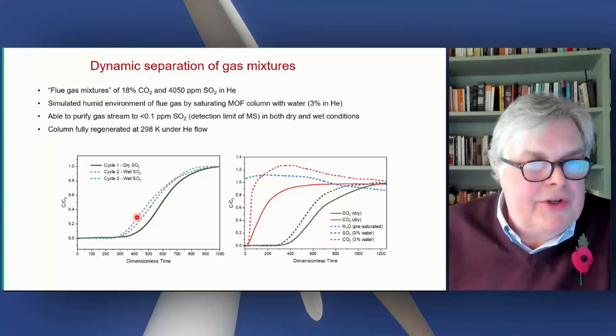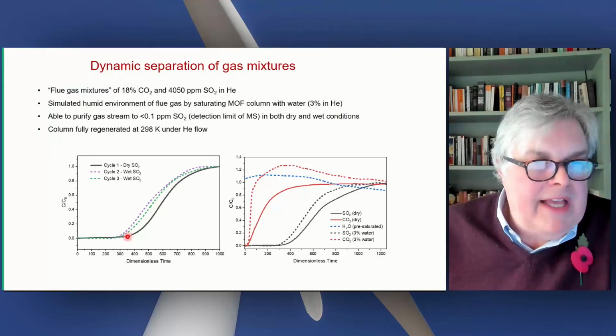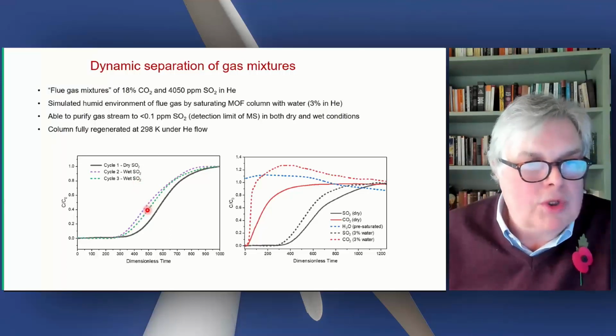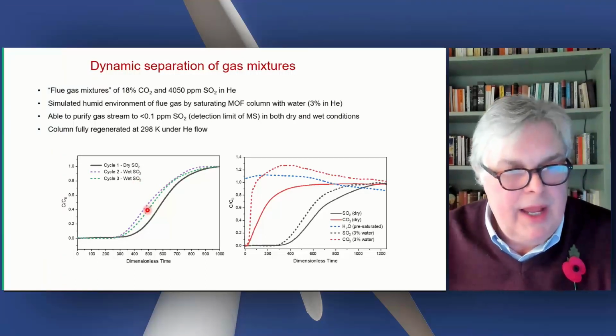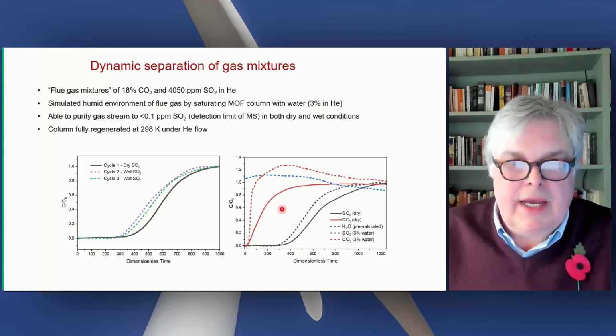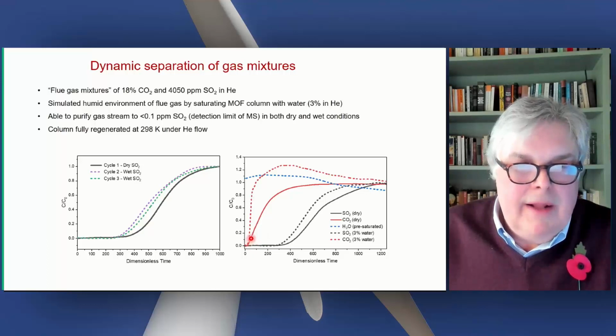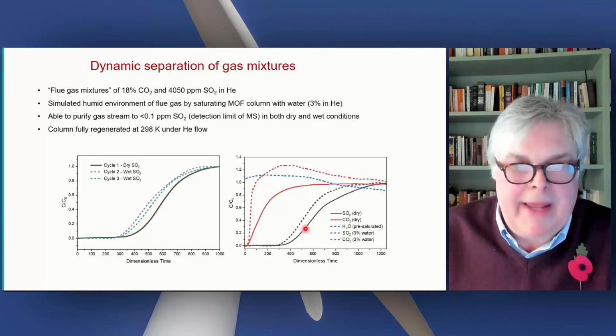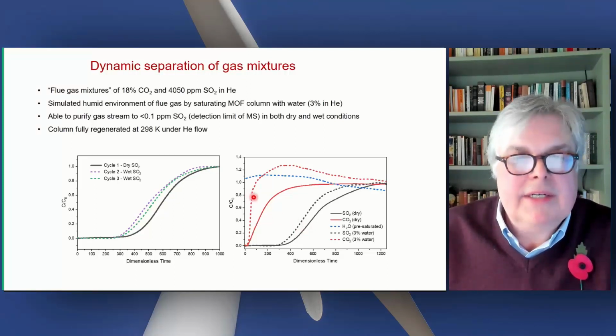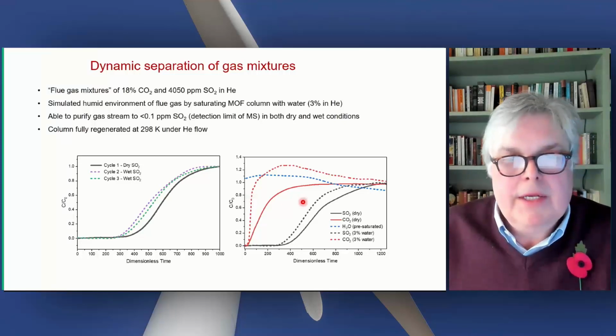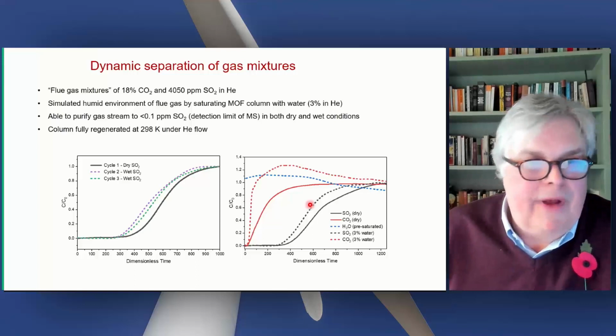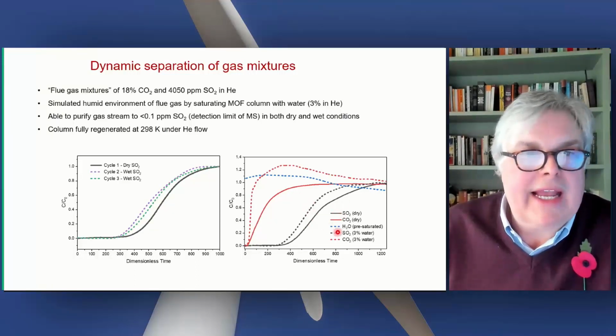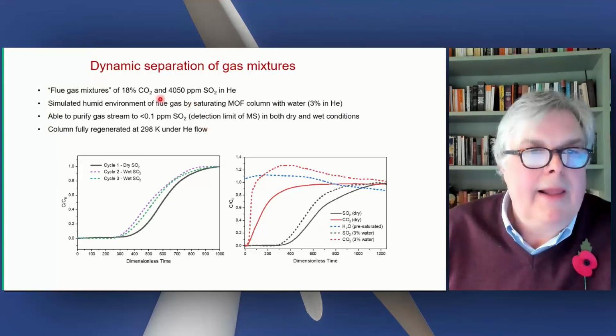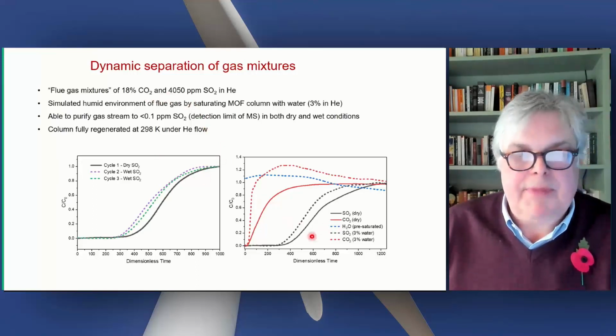And using this method, you can see this is the breakthrough of SO2. This is dry SO2, and these are 2 cycles for wet SO2. The water interacts with the SO2 and drags it through the column. And here is a breakthrough of a mixture. This is dry CO2 coming out, and this is dry SO2 coming out, and then this is wet CO2 and wet SO2 coming through. So you can see you can do wet gas streams, and of course looking at different concentrations. This particular one has 18% CO2 and 4,000 ppm of SO2.